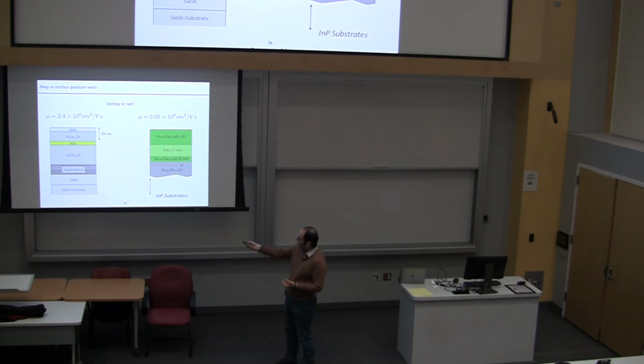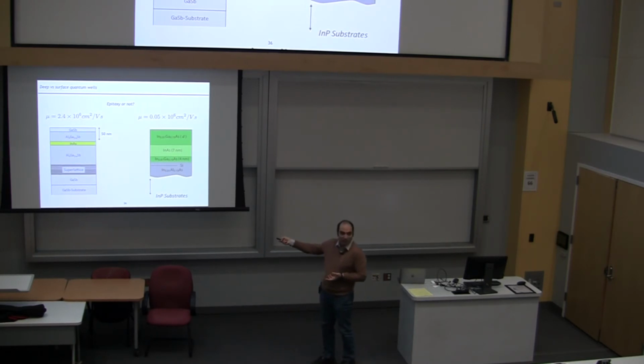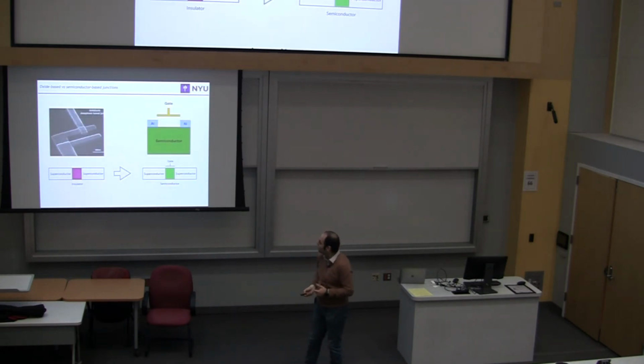And the difference with us is that these quantum dots are buried structures. They're 50 nanometers below the surface, right? So putting on a superconducting contact means that you have to etch down and then put the superconductor there. Here we are growing at the surface. Mobility, as you can see, is very different. It's 2 million there, and we are at 0.05, right? But we can put epitaxy in this, while there you have to do the device fabrication, right? So it goes back to my first point.